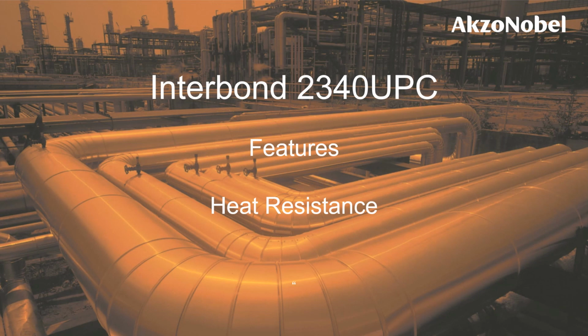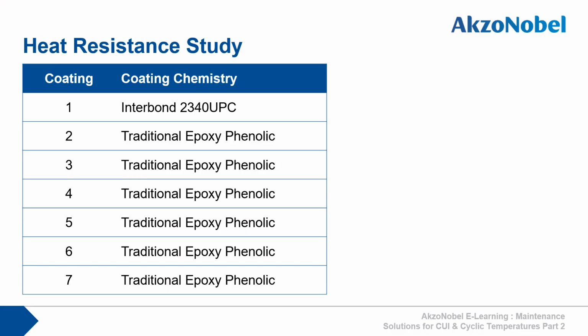Another important consideration when comparing epoxy phenolics is heat resistance. In this study, 2340 UPC was compared against 6 other traditional epoxy phenolics currently in the market. All of them are typically specified for service up to at least 200 degrees Celsius. All schemes were applied at 2 times 125 microns and all cured at 20 degrees Celsius for a minimum of 7 days before testing.